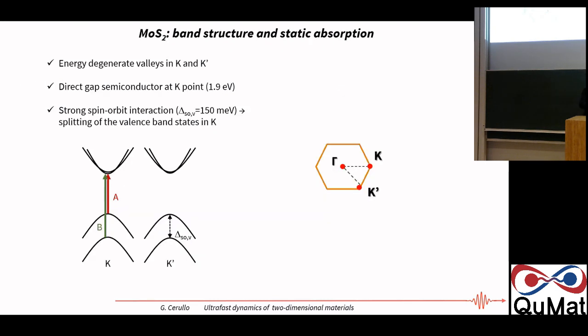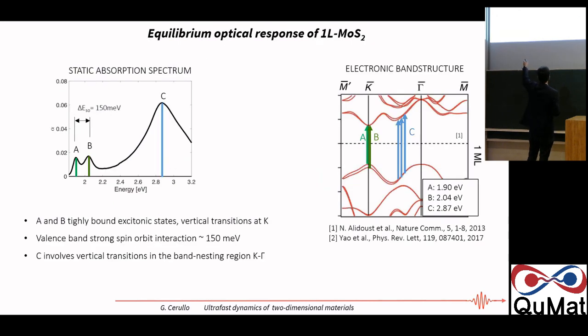Now, if you look at the band structure and the static absorption of these materials, you have two valleys, the K and the K prime valleys, which are energy degenerate. They have the same energy, and they both have direct transitions, and there is a strong spin orbit interaction that splits the valence band states. So the A and B excitons are really coming from this valence band splitting, which is on the order of 150 milli-electron volts in MoS2, and even higher in WS2, on the order of 450 milli-electron volts. So this is the origin of these A and B excitons, the spin orbit splitting in the valence band.